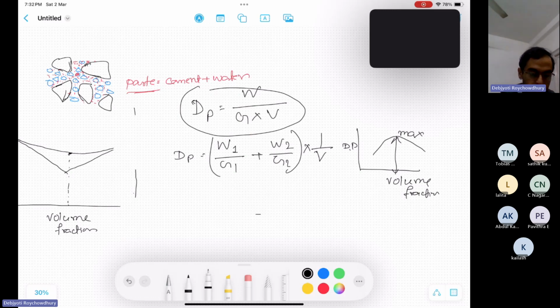So now let's choose the best proportion which gives the maximum packing density. This is the volume fraction; aggregate 1 and aggregate 2 are there. You find out by trial mixes that if coarse aggregate 1 is 60% and aggregate 2 is 40%, then it gives the highest packing density. So it is the best proportion, and you get it for the M20 mix. For the maximum aggregate size, 20 or 10, you can do trials and find out the packing density. This way you can find out the packing density based on experience.